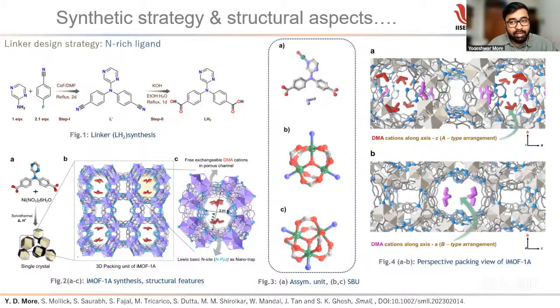So we need to be very careful about the selection of the MOF and its linker, because the linker can be functionalized, and the resultant MOF is going to have the geometry, topology, as well as the pore channels or pore voids in such a way, and the coordination geometry in such a way, that we exactly recover the uranium, not other ions. There will be some competition. A certain amount of other cations will come, but uranium should supersede. That is basically the prime goal.